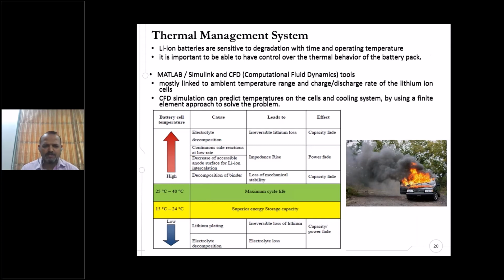So different software can give you the rate of charge discharge, with the ambient temperature range, and can predict the thermal issues. But one important thing is that these are highly volatile materials like electrolyte, which is going to decompose at very high temperature, which leads to a capacity fade of your battery pack. Then there are continuous side reactions going on between anode, cathode and electrolyte because there is ion transfer. So on the surface there is an impedance which can rise to a power fade. Then decomposition of the binder, these are the materials which can give mechanical instability.